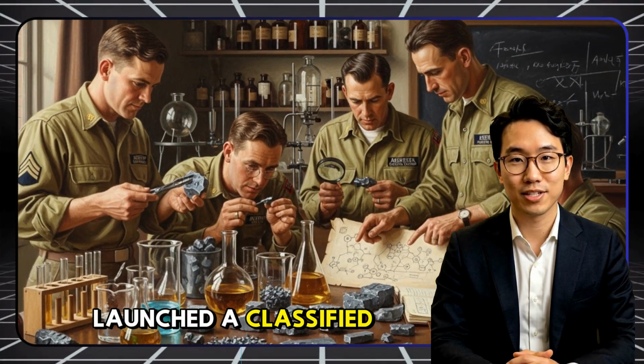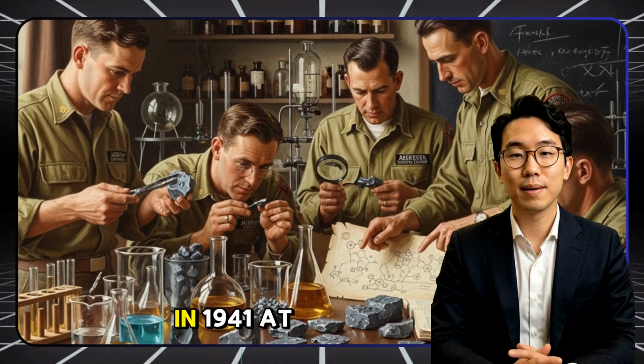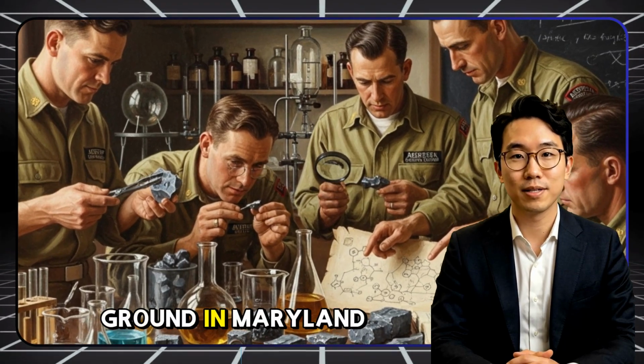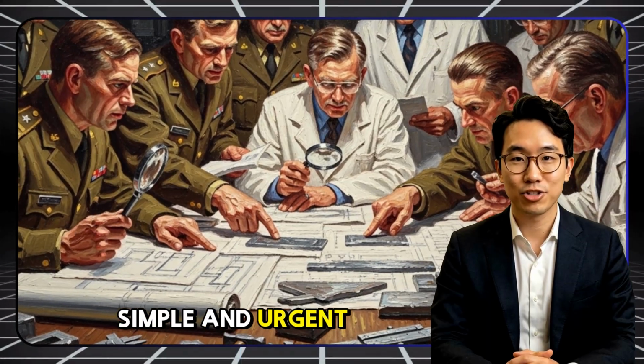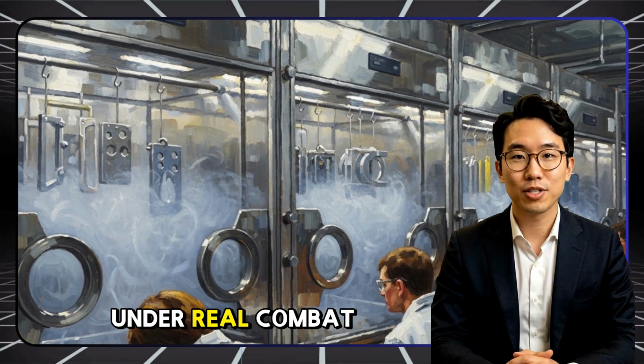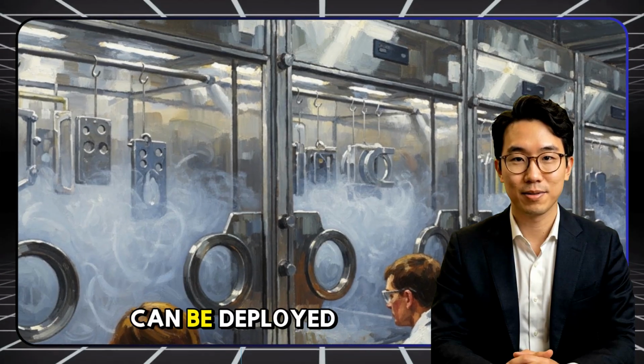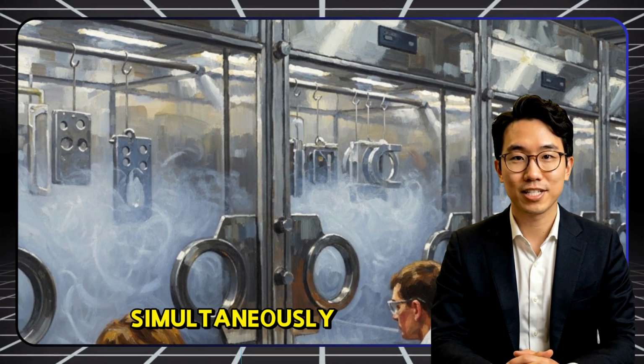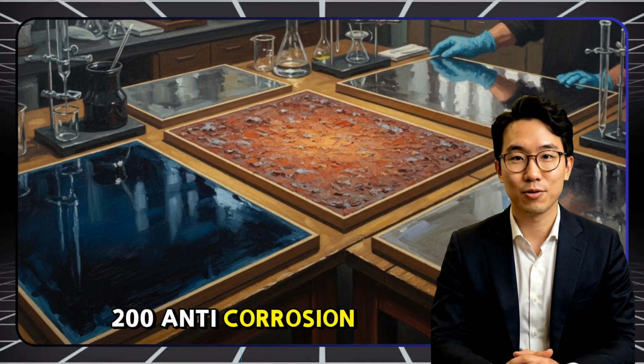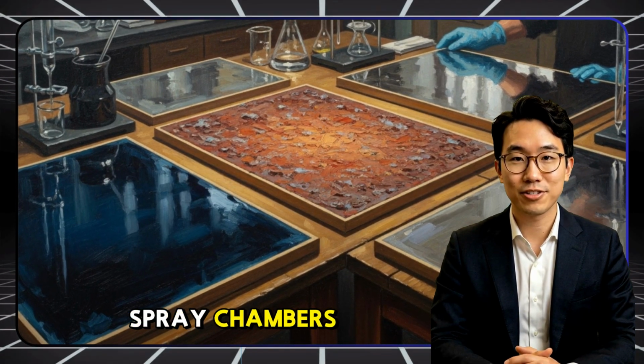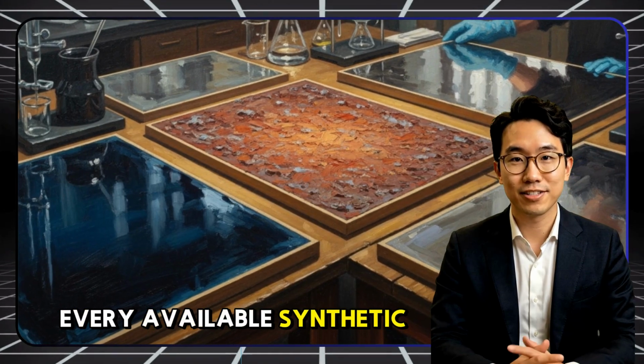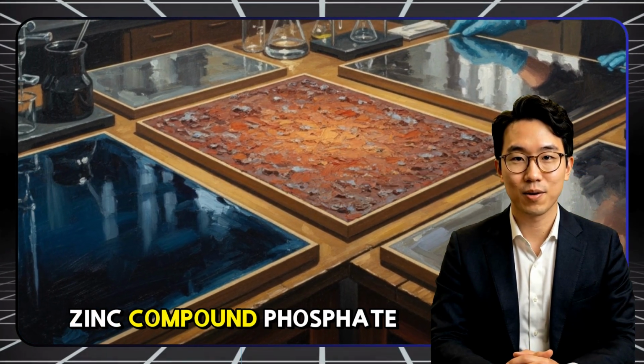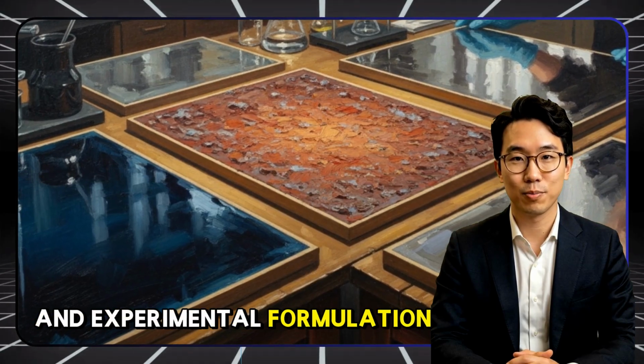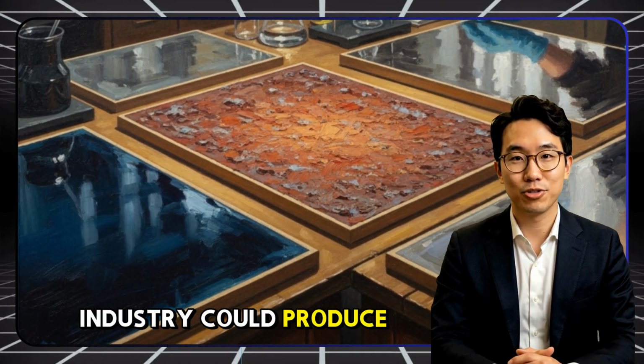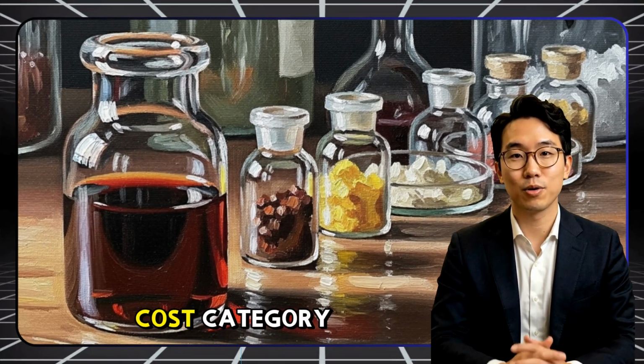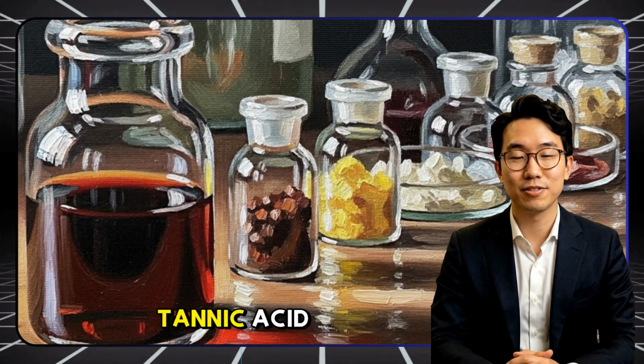The War Department launched a classified materials preservation research program in 1941 at the Aberdeen Proving Ground in Maryland. The mandate was simple and urgent: find a corrosion solution that works under real combat conditions at a cost and scale that can be deployed across 3 active theaters of war simultaneously. Researchers tested over 200 anti-corrosion compounds in accelerated salt spray chambers. Steel panels were coated with every available synthetic primer, petroleum-based inhibitor, zinc compound, phosphate treatment, and experimental formulation the American chemical industry could produce. And tucked away at the bottom of the list, in the low-cost category, they included a 4% solution of tannic acid.